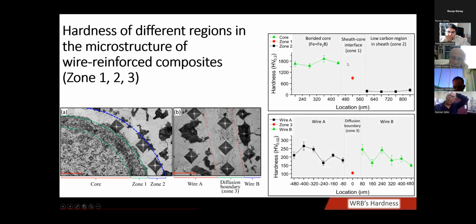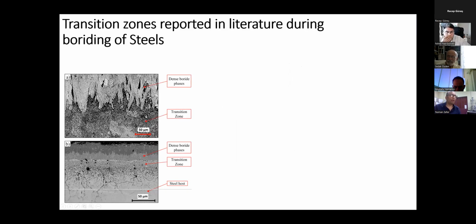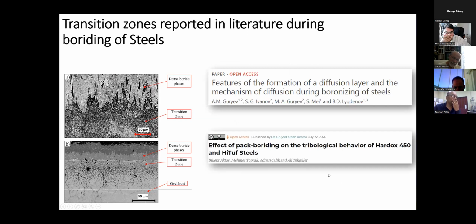These images show typically the same stuff which I have just said. Interwire boundaries, high hardness, low hardness, high hardness, and interwire boundaries, low hardness. Core, substantially high hardness. Zone 1, a little low, and then lower hardness. And while people were reporting the hardness of these transition zones, which are formed because of the presence of alloying elements in the steel, they have also reported low hardness in the transition zone. And these are some studies which have reported the hardness of this formation and of these materials.